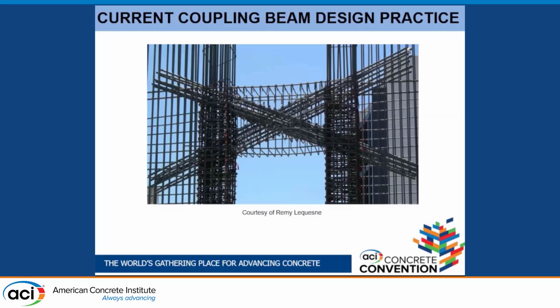This is a very complicated thing to build, not only because the diagonal reinforcement cages intersect in the middle, requiring the bars to be offset, but also because of the transverse steel required, for example when dealing with a special boundary element, which has fairly closely spaced transverse steel. You have to thread each bar through the edge or boundary region of the two walls being connected. This is a very labor-intensive and time-consuming operation. Sometimes these bars are so heavy that you need two people and maybe a crane to handle a single bar.